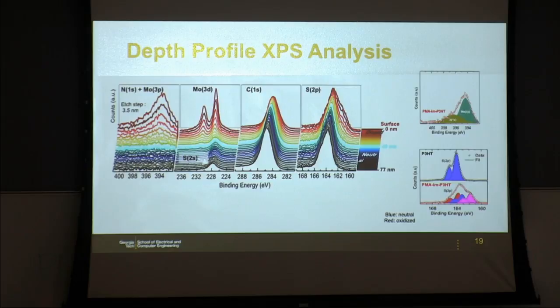And that's what's shown on this slide here. It's a depth profile of signatures of different atoms as you go from the surface of the film into the film itself. Okay? So it's a diffusion process, but it's a diffusion reaction process, which makes it really interesting, because if you had only diffusion and you just apply Fick's law and you wait long enough at steady state, basically the dopant is in the film entirely and you don't have a gradient or you don't have a constant concentration profile. But here, as the dopant penetrates into the organic semiconductor, it electrically dopes it.